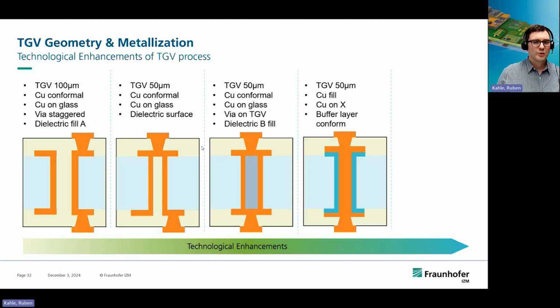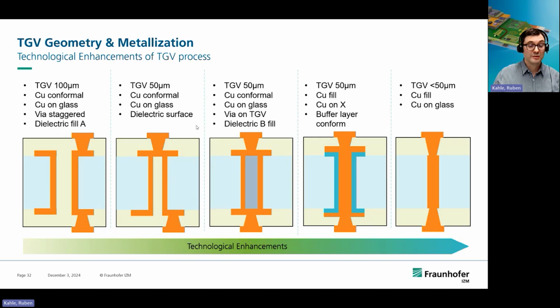Now, the next phase was to find out that you need a buffer layer somewhere in between copper that has a really higher CTE and more extreme differences of what the E modulus is. Now, the thermal stress is a product of CTE and E modulus, and of course this couldn't go on. So at a certain dimension and at a certain degree of copper volume to glass, for example, these things will simply break. Buffer layer helps a lot. And then, as been said, if you go down with the TGV even further, then you can use a copper fill. You can have copper on glass again, and this could still be reliable.